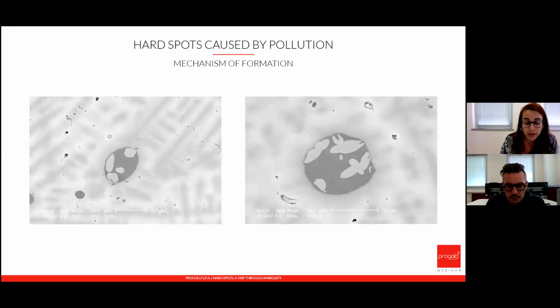As I said, we have these elements that are already inside the gold. These elements melt at a very high temperature, way higher than the usual temperatures that we normally use in our melting processes. So the particles are solid within the melted alloy. When we have the solidification, these discontinuity points, these solid particles that we have inside, are the first points where the metal starts to solidify. They are called nucleation points.